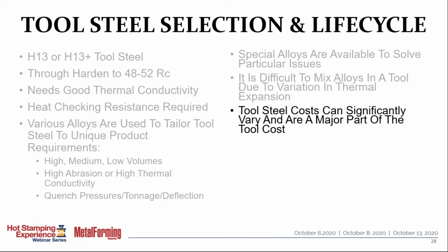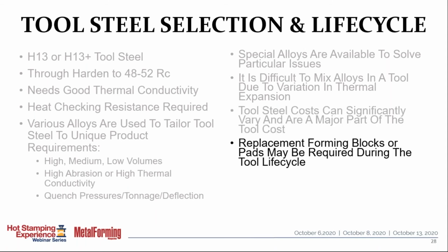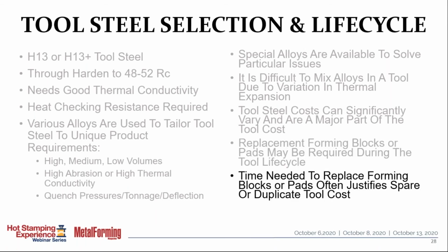Tool steel cost is a significant portion of the hot stamping tool, and it can significantly vary. There's some tool steels that are extremely costly compared to other tool steels, but in many cases, they're worth it for certain applications. Keep in mind that on hot stamping tools, you may need replacement blocks or pads during the tool life cycle. And the time needed to replace these forming blocks and taking the tool out of service often justifies spare or duplicate tools.